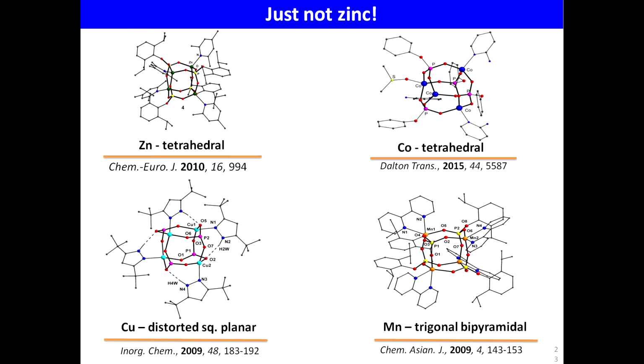Okay, as I said, zinc is what we started with. Then we realized there are multiple uses if you have a paramagnetic metal, for magnetic MOFs and things like that. So we put in cobalt, copper, manganese, and we could make all of these double 4 rings.